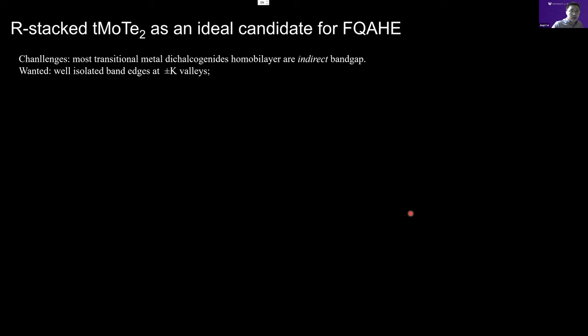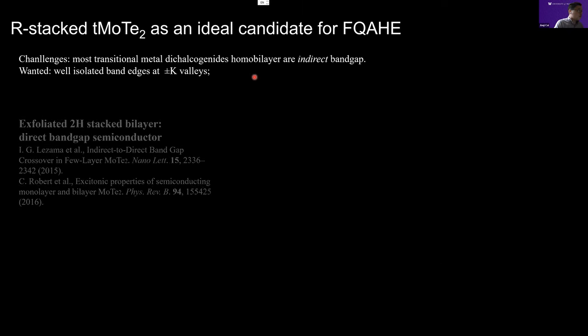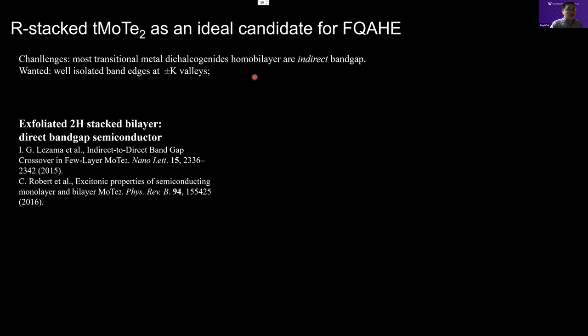Okay. So now we have the ideal probe, and we know our candidate is twisted MoTe2, but there is still some difficulty. Observation of those novel magnetic states requires a direct band gap, or very strong photoemission of the system. So what we want is well isolated band edges at the plus and the minus K valley. Actually, we are very lucky because twisted MoTe2 is proven to be a direct semiconductor.